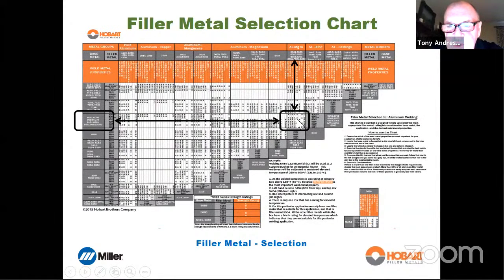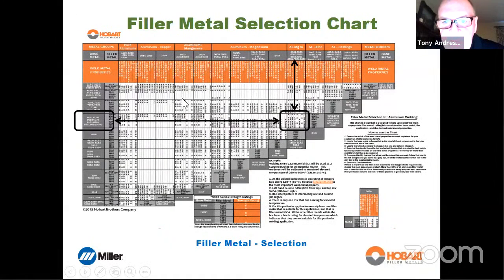If you are going to use this component at temperature, above 100, and that's 150 degrees Fahrenheit in service, you would not use 5356 because it's got more than 3% magnesium. And you could run into sensitization problems and stress corrosion cracking. So there's lots of issues here that you need to understand. And we could talk at least an hour probably just on filler alloy selection. But I want to give you an overview so you can dig deeper yourself. It is different. You've got to be careful and look out for these differences.